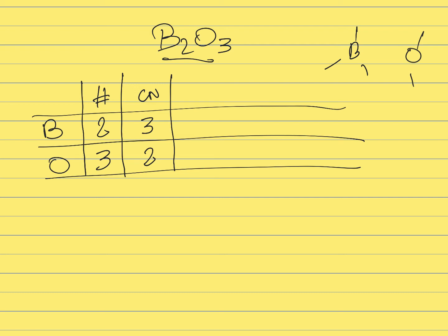It's important to have the coordination number, which is r, because this is going to give us the number of bond stretching and bond bending constraints created by these elements. In this case, the number of bond stretching constraints is given by r divided by 2, coordination number divided by 2.